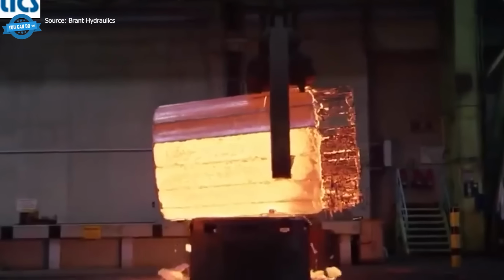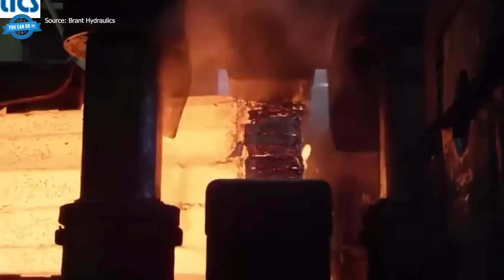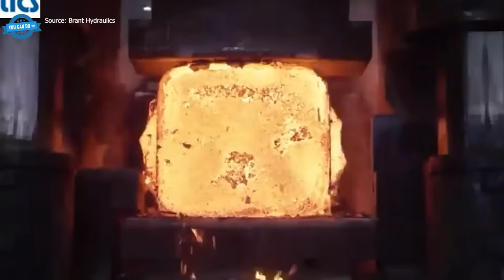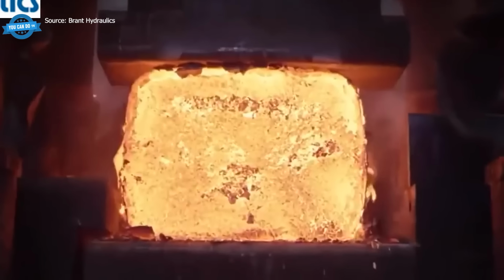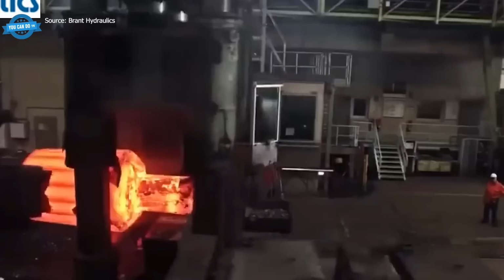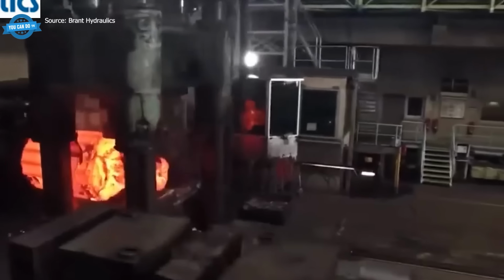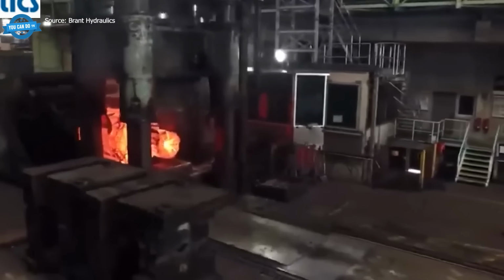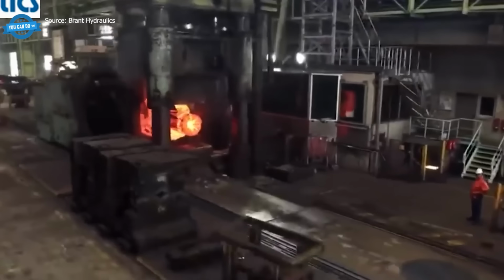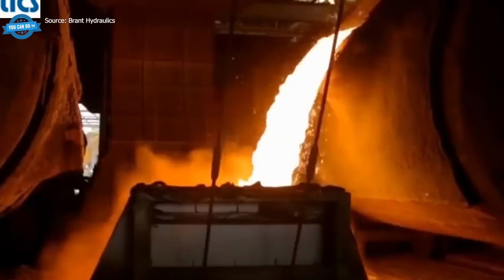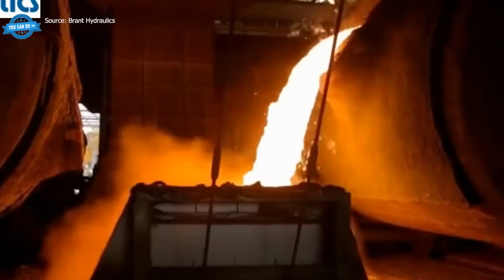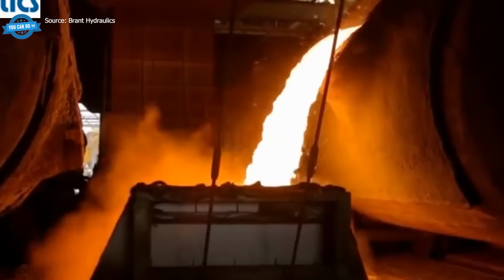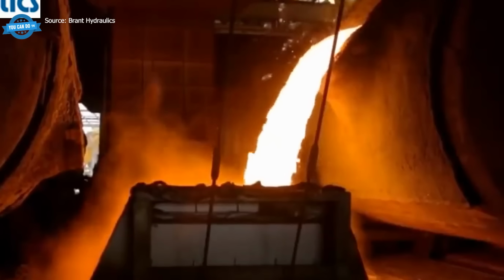Inside a steel mill, hydraulic cylinders don't have the option of failing. A jammed mud gun cylinder during a tap-out, a stuck cylinder on a continuous casting machine, a failed cylinder on a hot strip mill. Each one halts a chain that runs at thousands of dollars per minute. Steel mill cylinders cover the entire production chain.